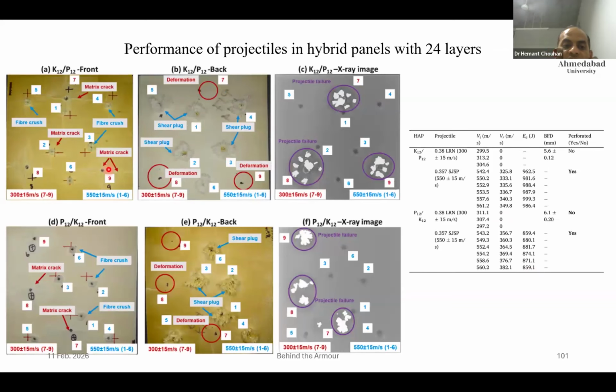And then we did a hybridization of the two, that is Kevlar 12 layers and PE 12 layers, and the X-ray of that. Again, the same results: we may slightly bring the residual velocity to lower numbers, but stopping is not done. But the other one continues to stop. But we could find what kind of damage occurs, shear plugging, fibrillation, stretching, those are the things which an academician or a researcher is interested in.